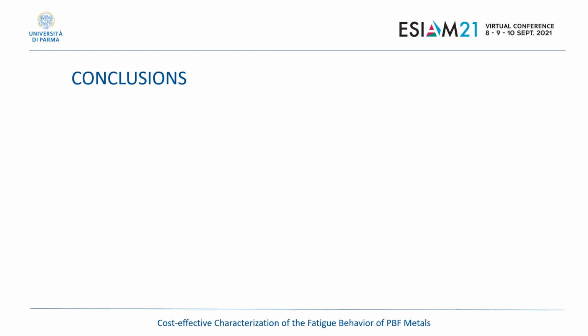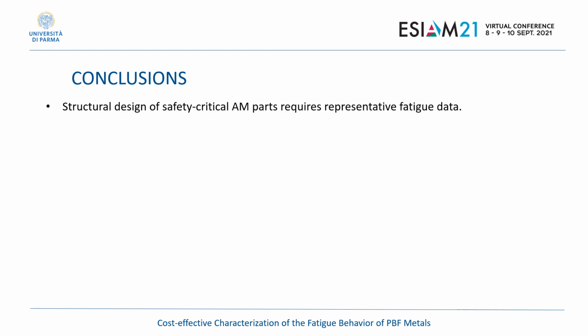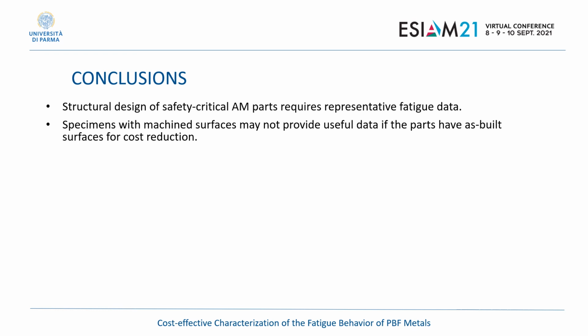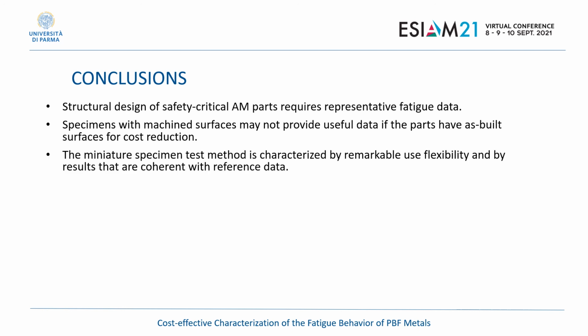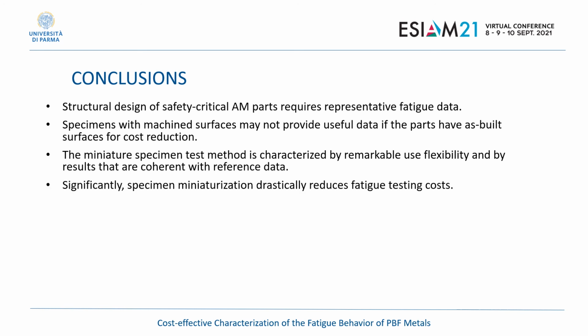We arrive now at the conclusions. First, the structural design of safety critical parts requires representative fatigue data. Specimens with machined surfaces may not provide useful data if the part has to have as-built surfaces for cost reduction. The miniature specimen test method is characterized by remarkable flexibility, demonstrated by experiments in this presentation, and by results that are coherent with reference data obtained with standard specimens.